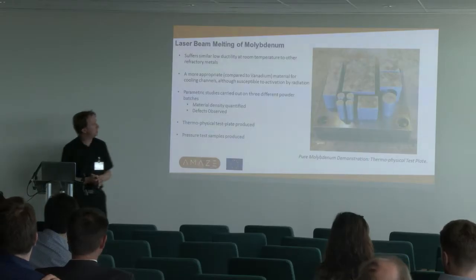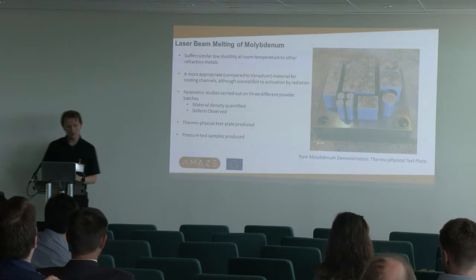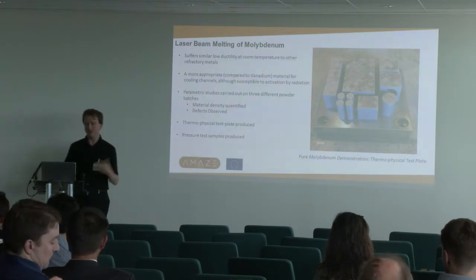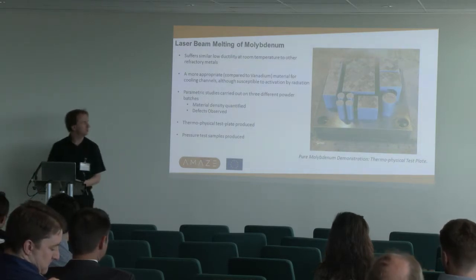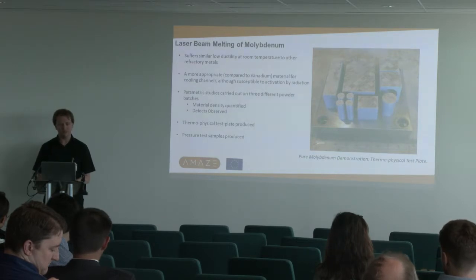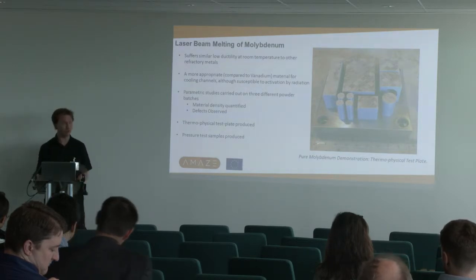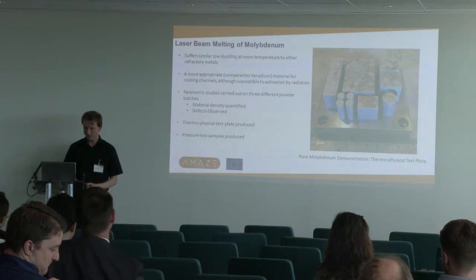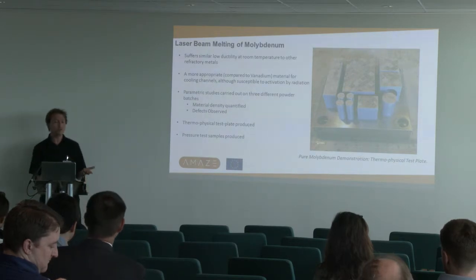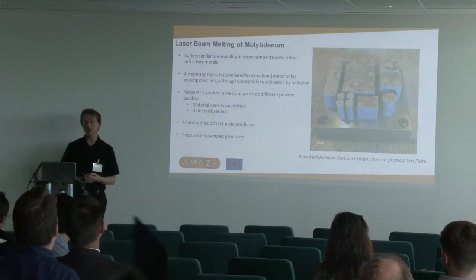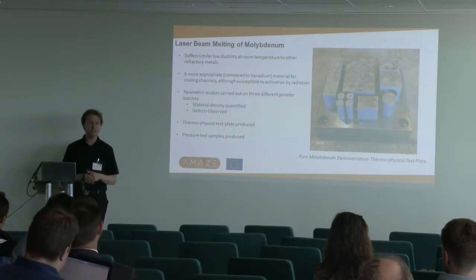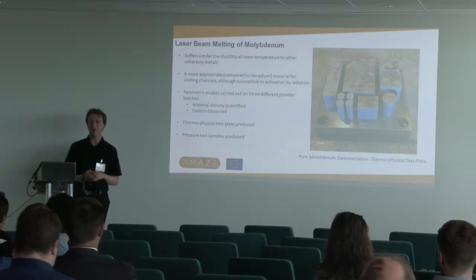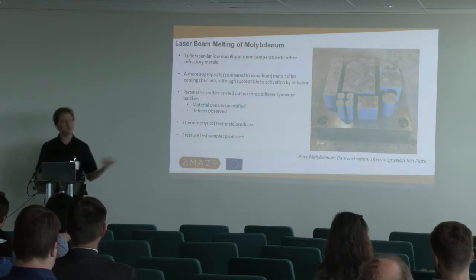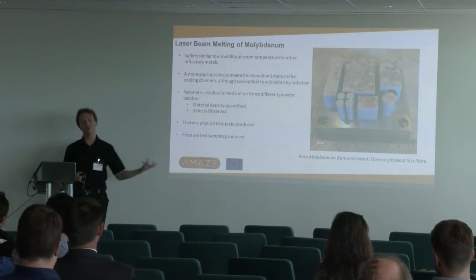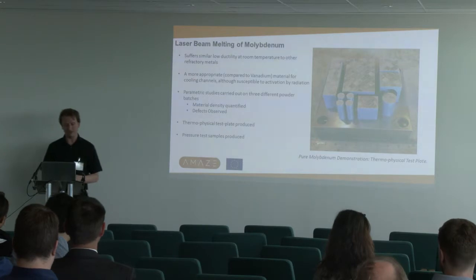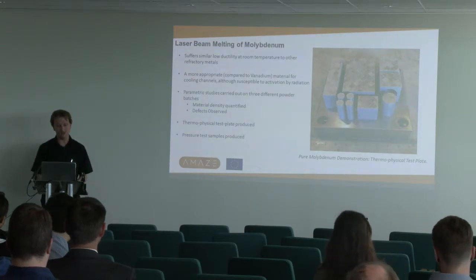Moving on now to molybdenum. So this suffers a similar sort of low ductility at room temperature, as is common with refractory materials, so it's quite challenging from that point of view. It's prone to cracking, basically, and rupturing. It's apparently more appropriate compared to vanadium, although it is still susceptible to activation. There's been a lot of talk about whether you can have selective isotope selection of molybdenum to use the more favorable isotopes for the application, and that's still ongoing, but it is of interest as a structural material.